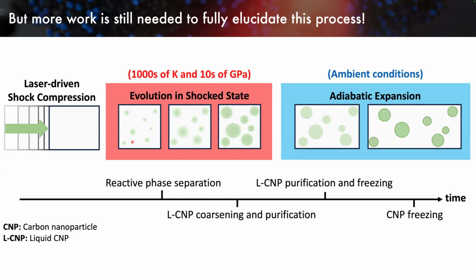And what that's going to do is drive a reaction-driven phase separation of the excess carbon in the precursor from everything else in that reactive soup that we've created, driving nucleation of these liquid carbon nanoparticles.